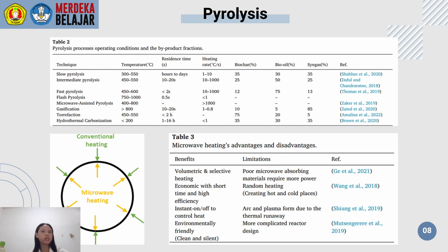In intermediate pyrolysis, the reaction is faster than slow pyrolysis but slower than fast pyrolysis. It occurs between 450 and 550 degrees Celsius, takes 10 to 20 seconds to complete, and produces less charcoal than slow pyrolysis. It is capable of processing a wider range of biomass, from larger particles to pellets and flakes, as well as materials containing nearly 40% moisture.